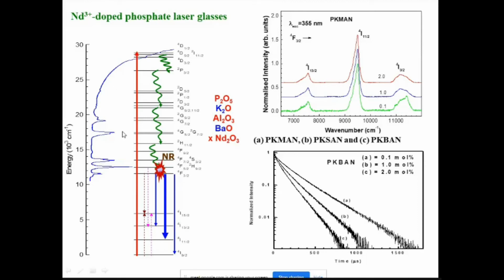So I can measure the absorption spectra, I can measure the emission spectra, I can measure the decay curve, and I know what the glass composition is. So I can optimize the glass composition so that I know which glass composition is going to give better luminescence properties. With glass, a nano glass is going to give better luminescence properties. All those things can be done. This is my research. Instead of neodymium, I can use the entire rare earth ions, not only neodymium. I can use erbium, I can use thulium, I can use dysprosium. There are 14 elements. I can choose whatever element I want depending upon the purpose, and I can vary the composition.